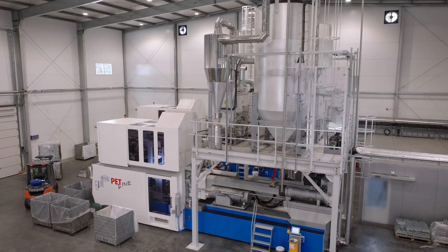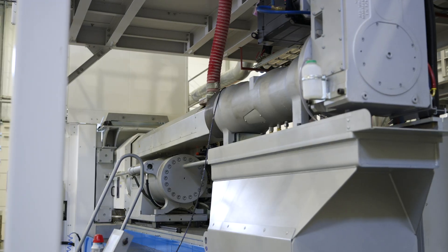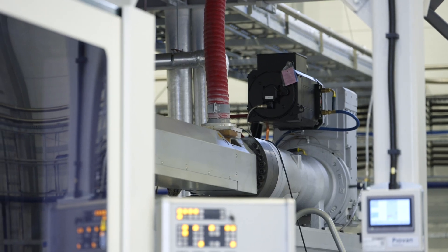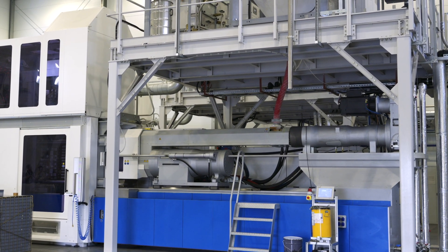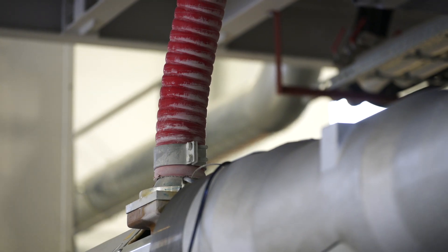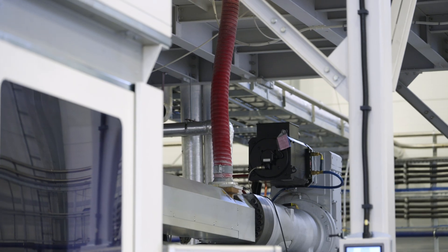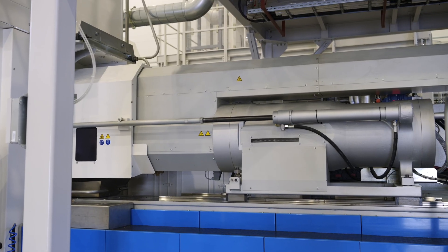The plastic material from the silos is then fed into the auger inlet. This is the first stage of the robotized plasticizing system. There, the plastic is heated to 280 degrees Celsius and becomes more liquid. Pigment or other components can be added at this stage.